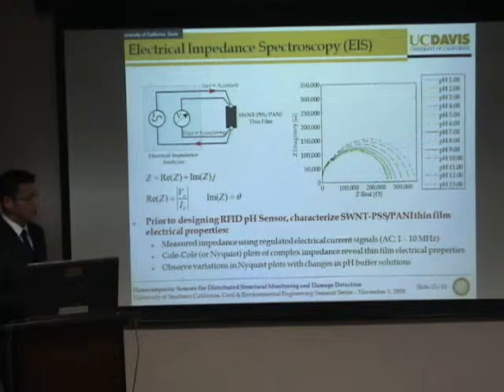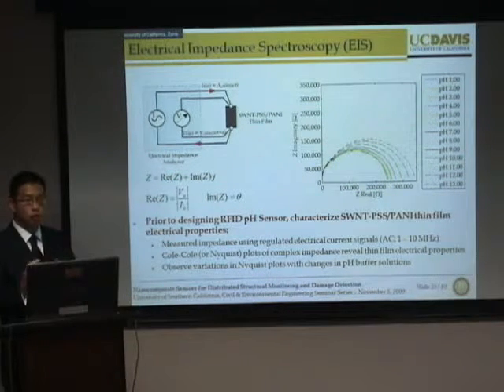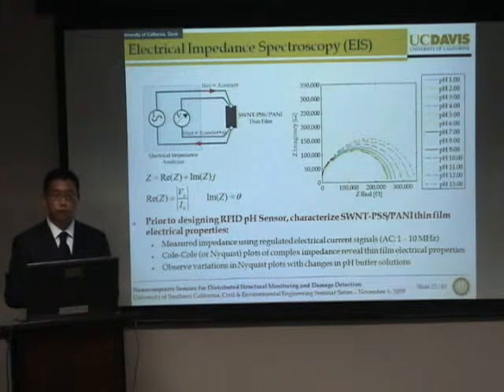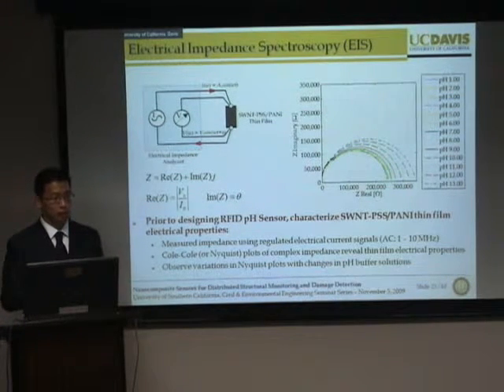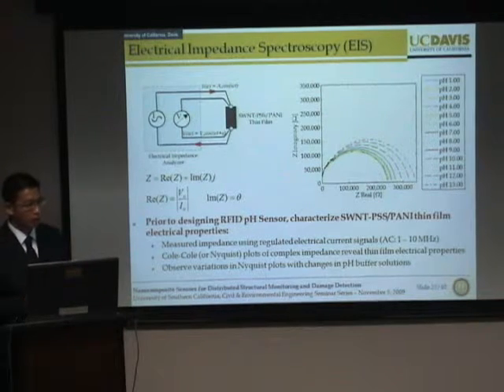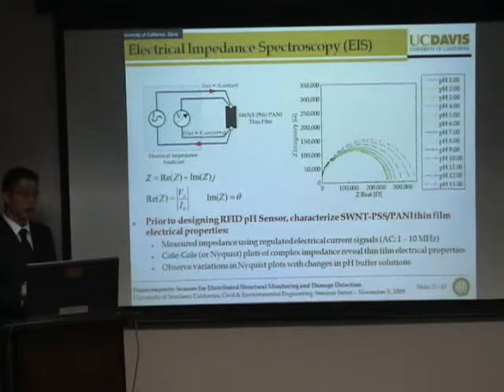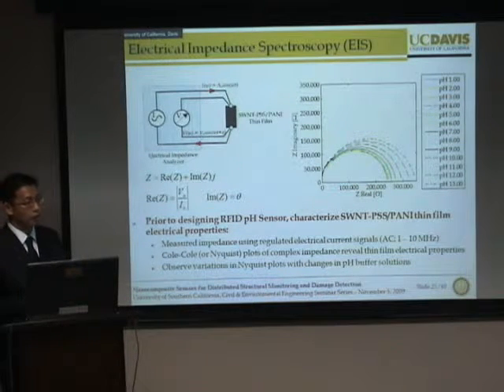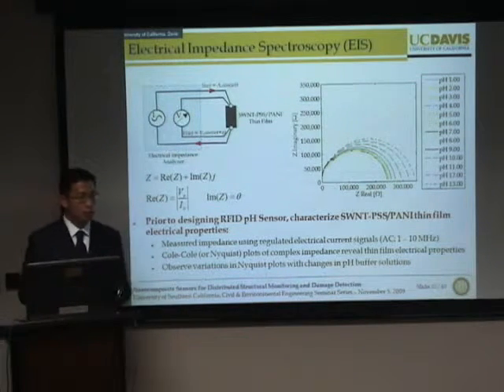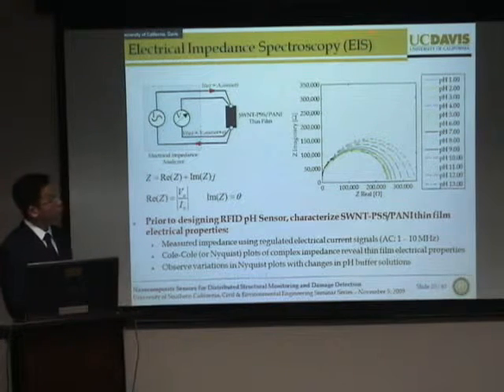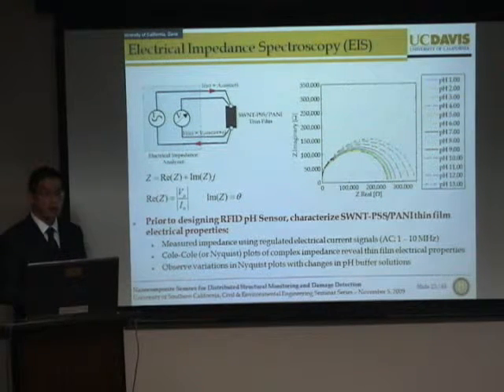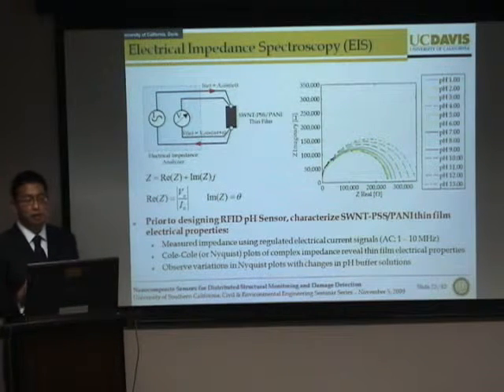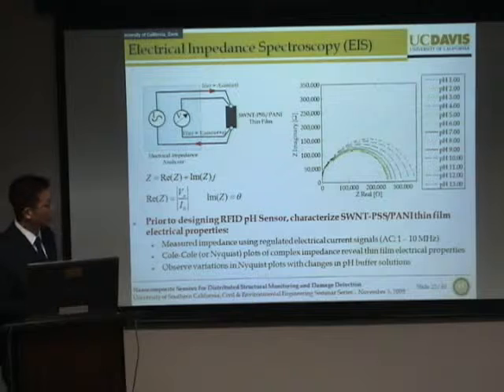Now, the objective that we want to achieve here, like I mentioned before, is to design a corrosion sensor that we can embed in reinforced concrete environments to detect the onset of corrosion by measuring changes in pH. Now, in previous studies where we characterized our Pani pH thin film, we've only been applying direct current and measuring its resistance. But we really need to take advantage of electrical impedance spectroscopy to look at whether the material behaves as a pure resistor or does it have some capacitive element or even sensitivity to pH to it.